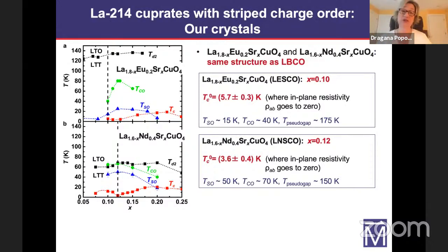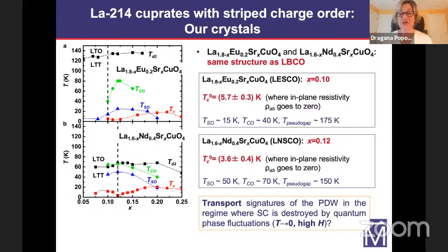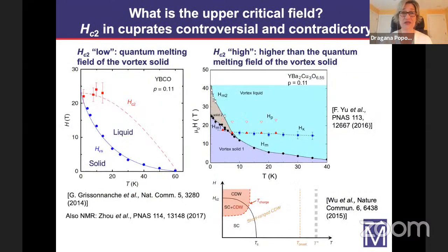So basically what we need to do now is apply magnetic field, suppress the superconductivity, and study the anisotropy by applying that suitable perturbation, the parallel magnetic field. However, this is actually easier said than done, because this means that we need to know when the superconductivity is actually fully suppressed. We need to know the upper critical field. And it turns out that this has been a highly controversial subject for decades in cuprates, and the interpretation of the experiment has been contradictory.